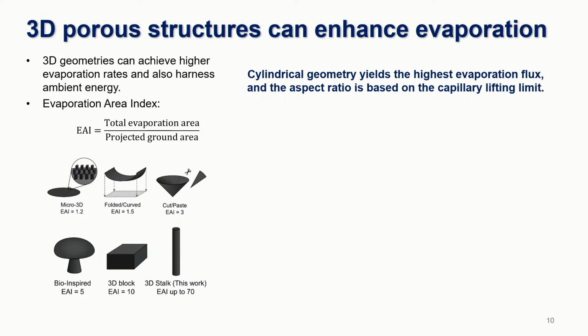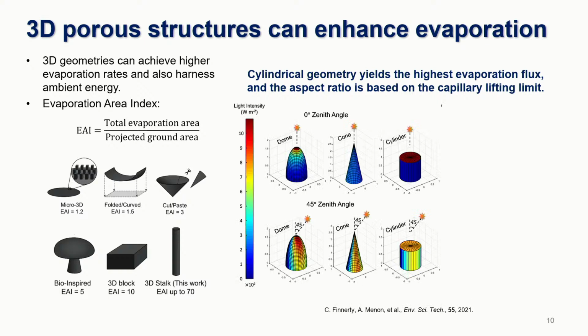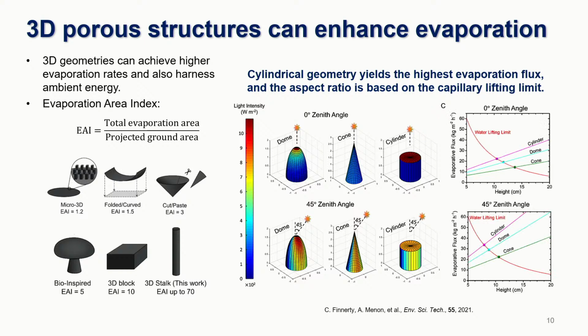So you get a much higher projected area, which we call this evaporation area index. And then we looked at what geometry would give us the best performance under sunlight. So if you have solar noon as a 0-degree angle, so the sun is vertically above, or at a 45-degree angle, we looked at which geometry allows you to maintain the highest temperatures for evaporation throughout. And what we see is we can get the highest evaporative fluxes at both the 0 and the 45-degree angles if we use a cylindrical structure among these different ones that we looked at.